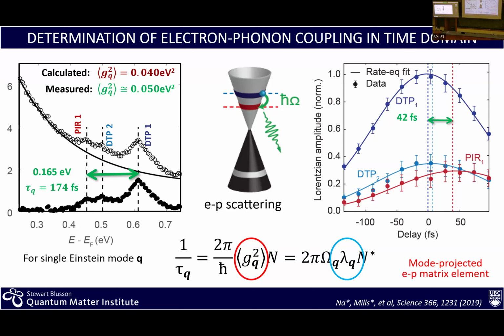Now, when you're comparing neutron or photon emission or scattering versus this, it's basically the question that was asked before. What are the advantages and disadvantages of each probe? Electron-phonon scattering will depend on the K of the electron. So which state are you looking at, and to which state are you coupling, and with which phonon, of course, as well. The different techniques will give you, in some cases, something specific for a Q, integrated over all possible momenta for the electrons, or specific for a K, integrated over all possible Qs for the phonon, even for a single branch, say. In this particular case, by having knowledge of the band structure and of the optically allowed transitions that you can use, you can position yourself and extract that information for a specific K and specific Q.